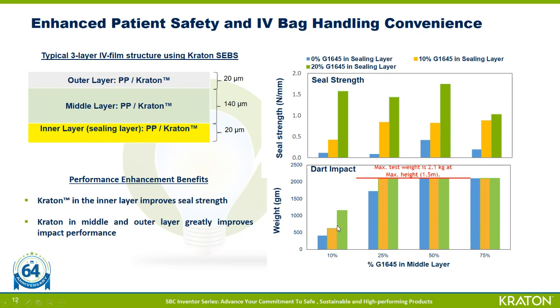What we can also see is that as a function of G1645 in the middle layer, beyond 25% addition of G1645, the bags really don't undergo breakage even after the maximum weight of 2.1 kg was reached. So these two data sets together show that 10 to 20% G1645 in the inner sealing layer significantly improves the seal strength, and 25 to 50% loading of G1645 in the middle layer highly improves drop dart impact performance.